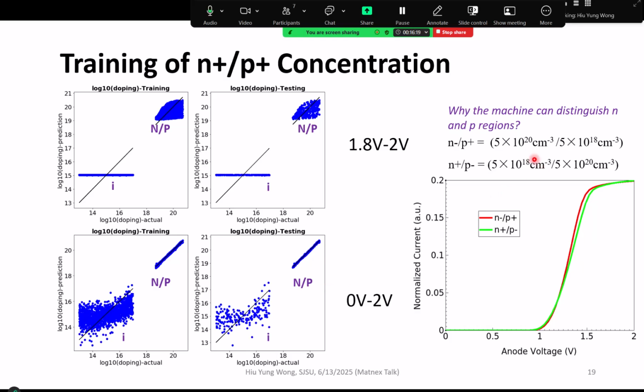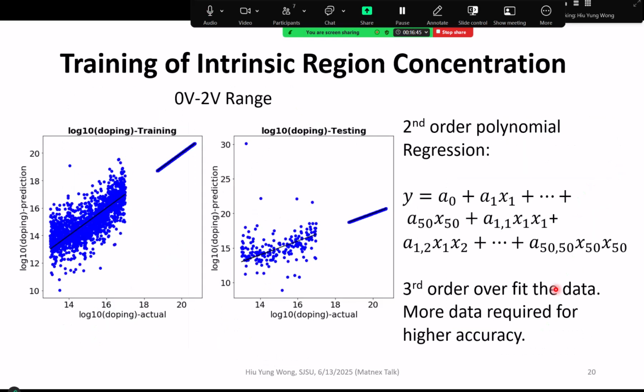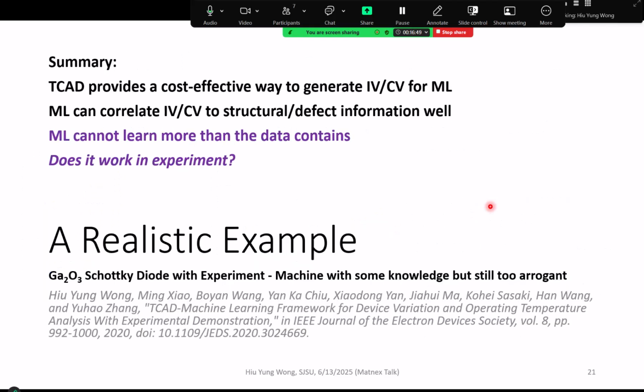Then why? So we try to plot the curves where one has a high N-type doping and low P-type doping, and another has a low N-type doping and high P-type doping. We do see that they have a different shape due to the different mobility model. So it means that the machine was able to capture all these details that a human cannot learn easily. I will skip these slides. This is just for the intrinsic region, not very important.